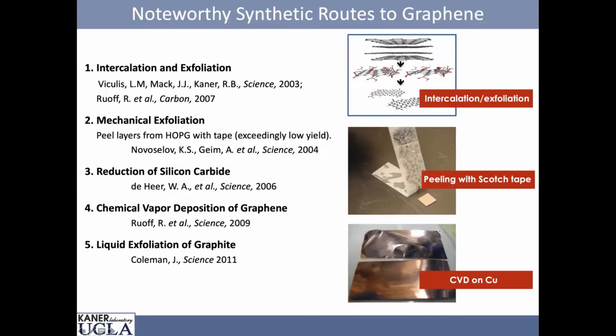If you want electronic grade material, you think about chemical vapor deposition, and Rod Ruoff showed us how. Let me grab a laser pointer here to make this a little bit nicer. All right, we've got a laser pointer. So with chemical vapor deposition, you can heat methane or some other form of carbon to 1,000 degrees, and with a little bit of hydrogen present, you can deposit it on copper. You can grow this single layer, and then you can etch away the copper, put a photoresist on, and you end up with graphene. So if you want to make electronic grade graphene, that's probably the way to do it.